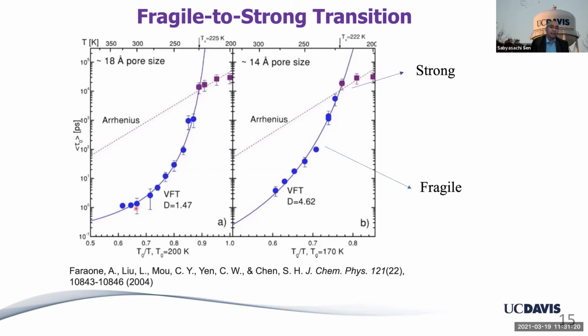high temperature. But as you lower the temperature, this is as a function of reciprocal temperature, so temperature goes down to the right. As you lower the temperature below a certain point, it ceases to be non-Arrhenius and behaves in a pretty Arrhenius fashion. So activation energy becomes independent of temperature. And people assign this behavior to a fundamental transition of water from fragile. This is called fragile behavior, again going back to Austen Angell's influence in the literature. He's the one who coined these terms.